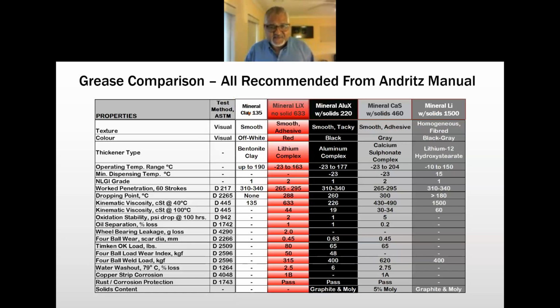A mineral-based clay grease. Here's a mineral-based lithium complex grease with no solids in it. Here's a mineral-based aluminum complex grease with solids, graphite and moly. There's a mineral-based calcium sulfonate grease with solids, 460 base oil, and 5% moly. Here's a mineral-based straight lithium grease with solids, 1500 centistoke base oil viscosity right here, with graphite and moly in it. So their grease requirements are really not based on scientific studies or working with one supplier. They just pretty much had suppliers come in and demonstrate the greases, and if the bearings last long enough, great, it's approved. So that's pretty much the Andritz approach.